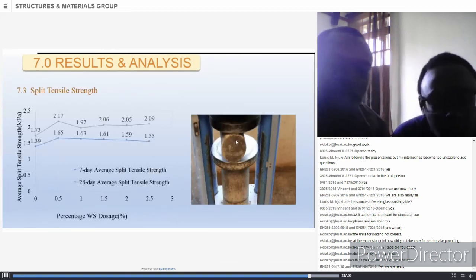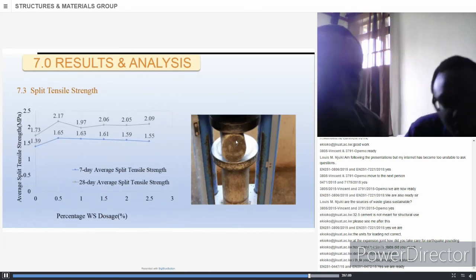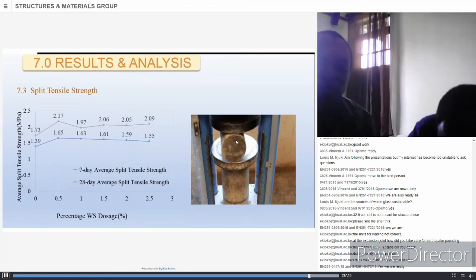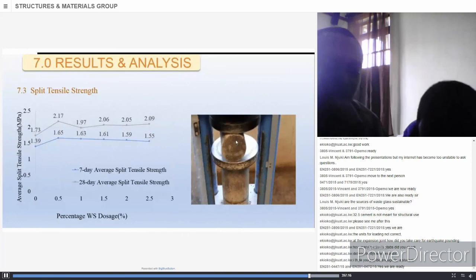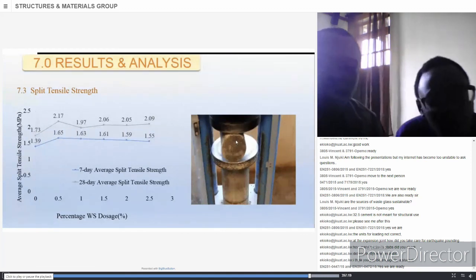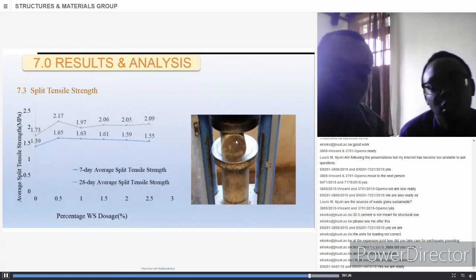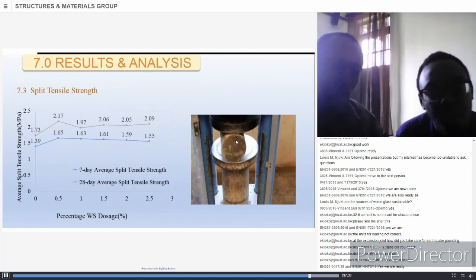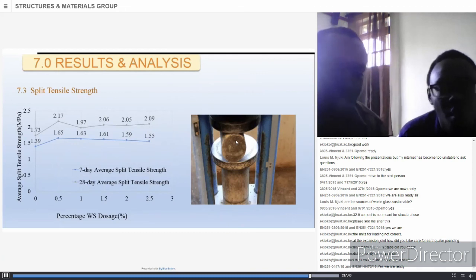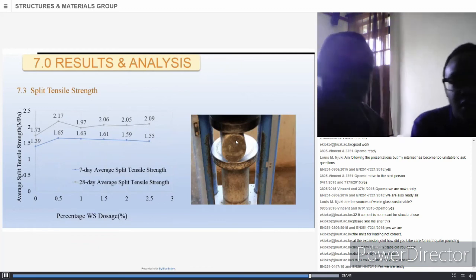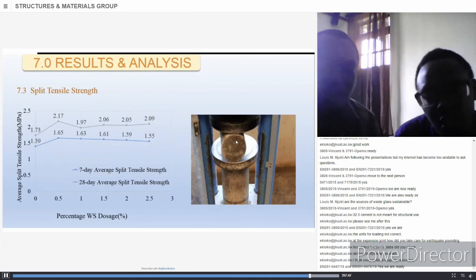The next result was on split tensile strength, where there was an increase as we continued to increase the percentage of wheat straw in the concrete matrix. There was an increase from plain concrete to 0.5% dosage, then a decline, then an increase from 1% dosage to 2.5%. This can be attributed to the addition of wheat straw, but it goes up to an optimum of 0.5%, after which there is no significant bonding effect of wheat straw on the concrete matrix.